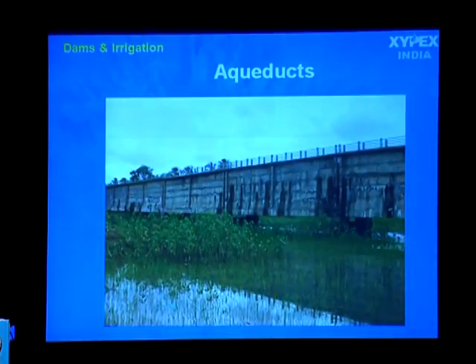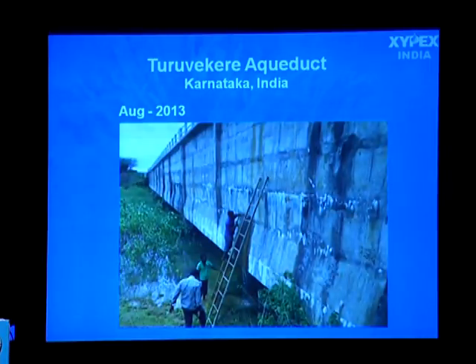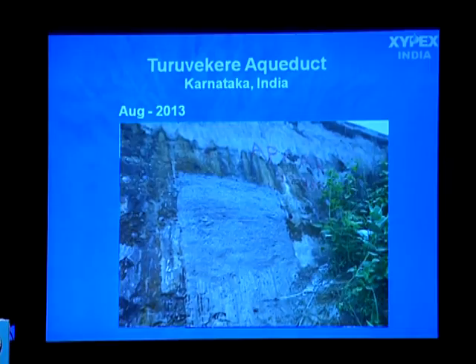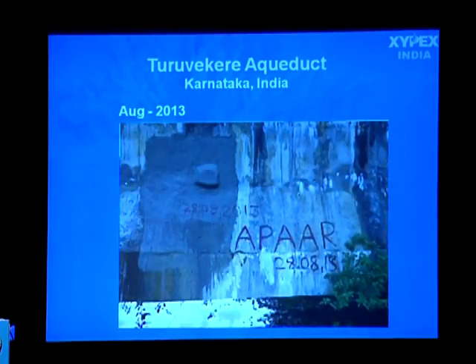Let me share with the house very quickly one of the aqueducts that we did right here in the state of Karnataka, the Turuvekere aqueduct, where again we did the field trial in August 2013 using the same material, and this trial was done on the outside of the structure, which means the negative side treatment, against the hydraulic pressure. We did a small patch. You can see on the screen this small patch was using this crystalline material, and then we left it there for observation for a couple of months.